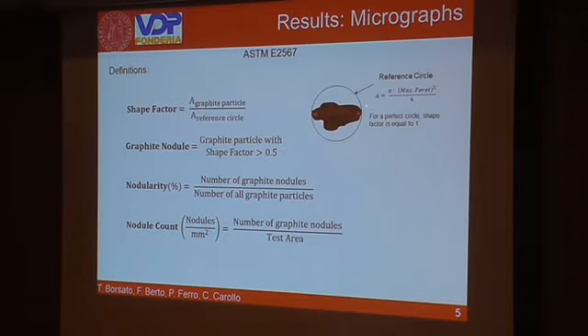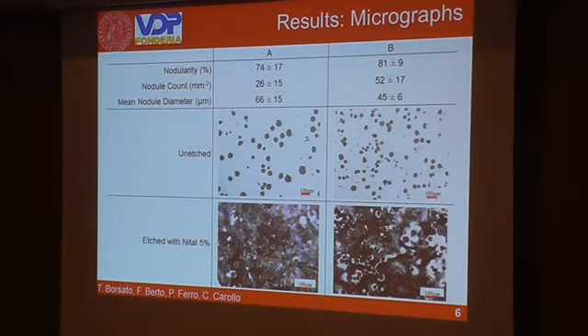A graphite particle is classified as a graphite nodule if this shape factor is greater than 0.5. The percentage nodularity is the ratio between the number of graphite nodules and the number of all graphite particles present in the casting. The nodule count is the number of graphite nodules per square millimeter. The results of the micrographs taken for casting A and casting B are shown in this table.